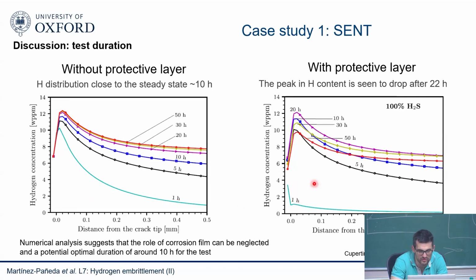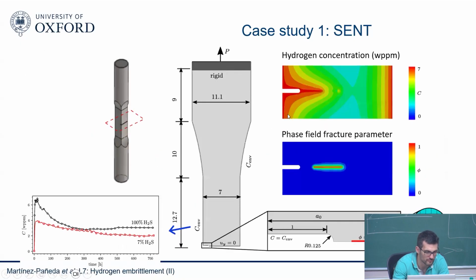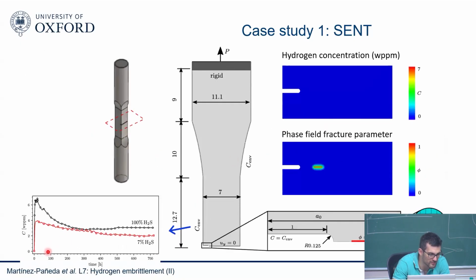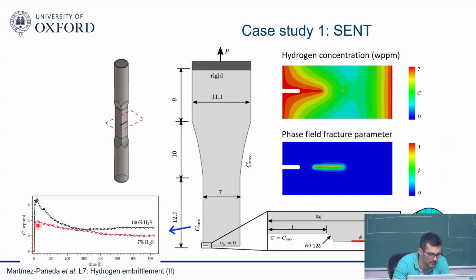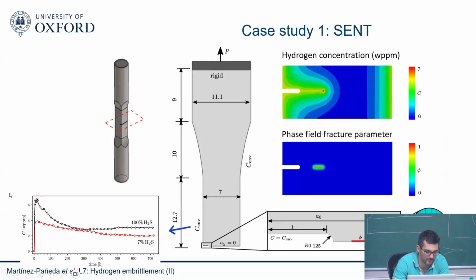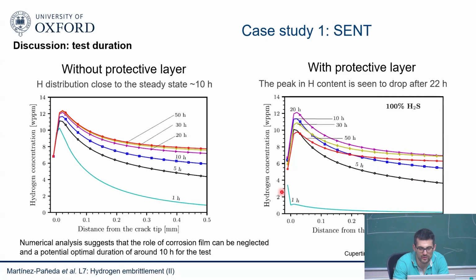And we see this. Initially it's growing up to 22 hours or so. So 10 hours is here, 20 hours is here, but then it starts going down, actually. So this is not very realistic. We reach a peak in 22 hours, but then it starts going down. So the hydrogen concentration does increase, but then it starts going down. But anyway, the picture doesn't change.